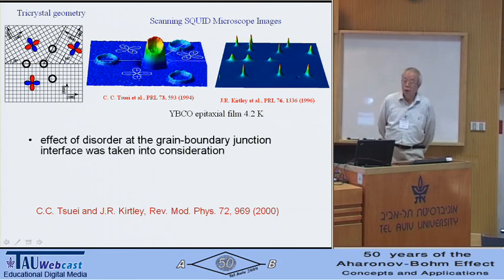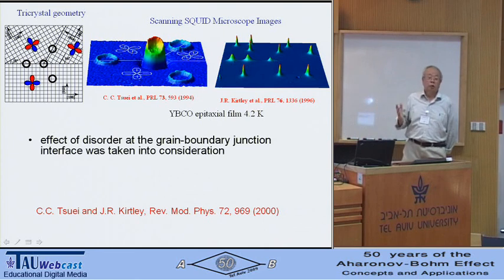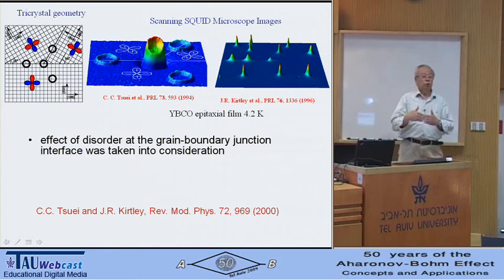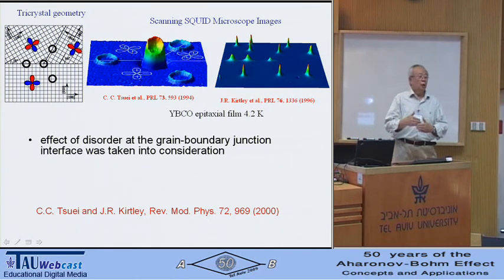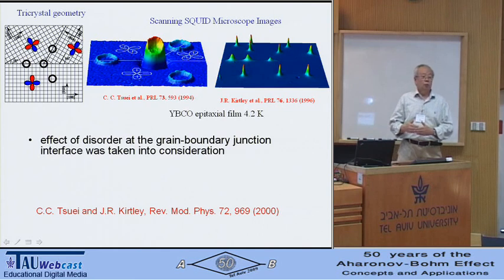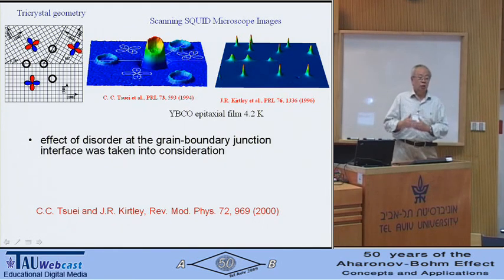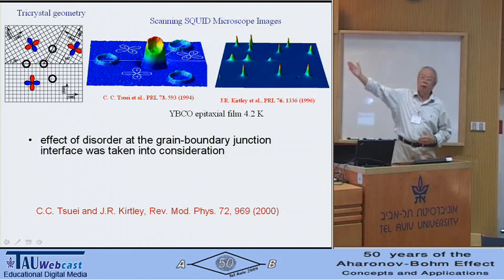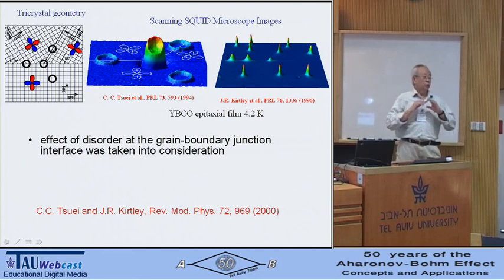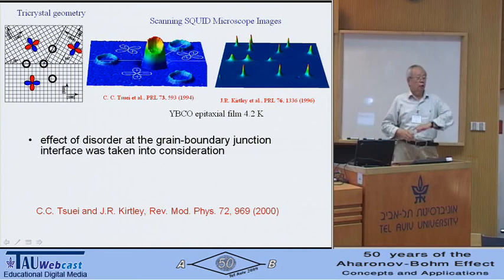Now I want to mention that when I designed this experiment, I took into account that the grain boundary junction interface may not be ideal. So I used the formula of the Sigrist-Rice clean limit as well as the formula I developed for maximum disorder. So in other words, this design is foolproof. Regardless of how bad the junction interface is, as long as you have a supercurrent flowing, you will get a half-flux quantum if it's a D wave.